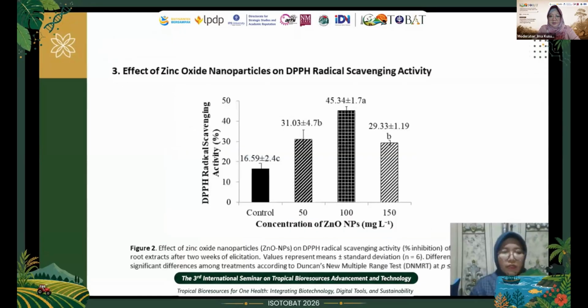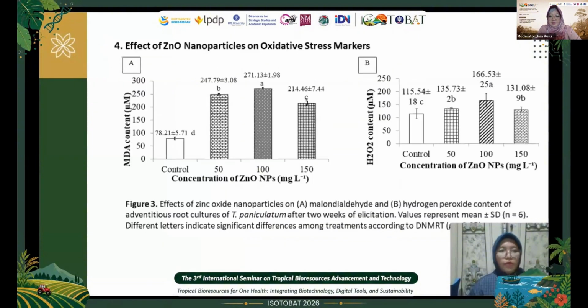Effect of zinc oxide nanoparticles on DPPH radical scavenging activity. Zinc oxide nanoparticle elicitation significantly enhanced the DPPH radical scavenging activity of adventitious culture compared with the control. Effect of zinc oxide nanoparticles on oxidative stress markers. Zinc oxide nanoparticles significantly affected the level of MDA and hydrogen peroxide in adventitious culture.